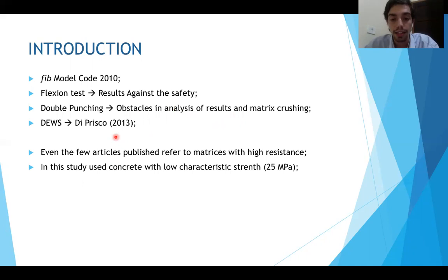Finally, there is the DEWS test, double edge wedge splitting, proposed by Di Prisco in 2013, a test with a more difficult preparation, but which provides results that are easy to read. It was the method used in this research. The literature on FRC at high temperatures is very scarce, and the published articles refer to high resistance matrix. In this research, we used low strength concrete, class C25, common in the city of São Paulo and throughout Brazil.